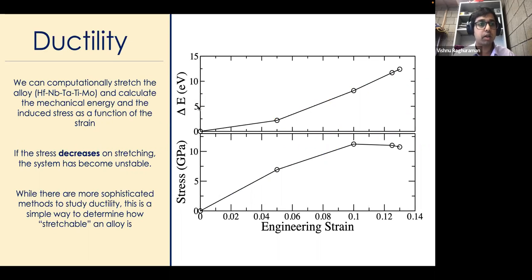Essentially, in our calculations, we can define a geometry file in which we define all the positions of your unit cell, and you would specify your lattice vectors. So if you then just change one of those lattice constants, so if you want to stretch a system along Z, you would just change the lattice constant in that direction by say 5% or 10%, and then you would recalculate. You would redo a DFT calculation, and then get a relaxed structure at that strain, and then calculate the forces and calculate the energy. Then from that you can get these types of plots.